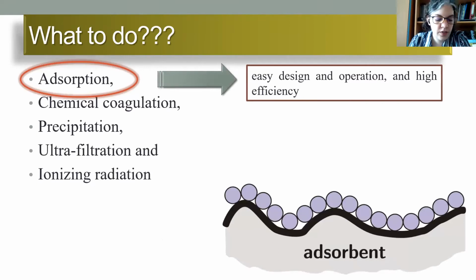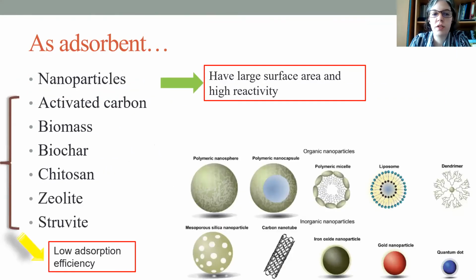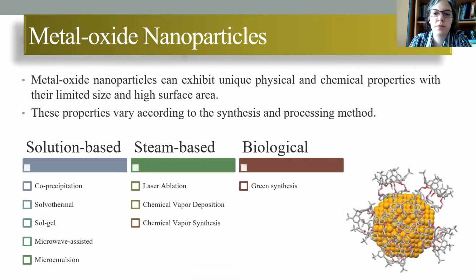In order to prevent the environmental damage of these dyes, wastewaters are treated using many methods such as adsorption, chemical coagulation, precipitation, ultrafiltration, and ionizing radiation. However, adsorption comes to prominence due to its easy design and operation, and also its high efficiency. As adsorbent, many materials can be used, like nanoparticles, activated carbon, biomass, biochar, chitosan, zeolite, and struvite. However, except for nanoparticles, these materials have low adsorption efficiency. On the other hand, nanoparticles have large surface area with small sizes in nanoscale, and they have high reactivity. Among these nanoparticles, metal oxide nanoparticles can exhibit unique physical and chemical properties with their limited size and high surface area. And these properties vary according to the synthesis and processing method.